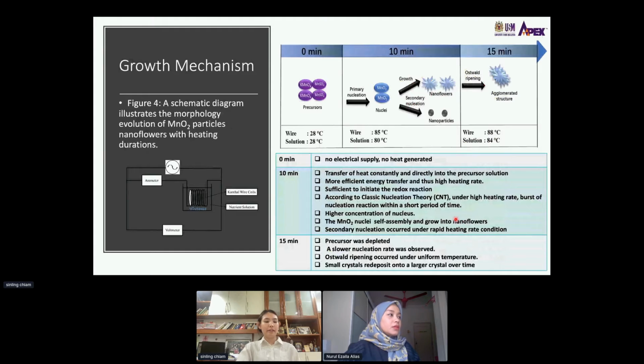So combining the characterization results, a growth mechanism for the MnO2 particles synthesized using the localized heating method is proposed. At time equal to 0 minutes, since there is no electrical supply, no heat is generated from the wire. So the temperature of the wire and solution remains at room temperature. At this time, no manganese oxide particles were synthesized.